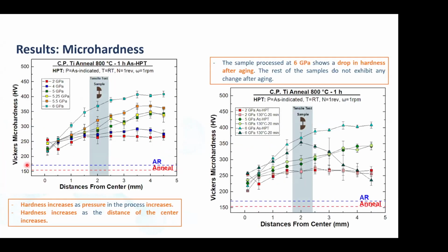So here is plotted the hardness of this kind of material against the distance from the center. And then you can see the effect of pressure on the hardness and the distance from the center. So 2 gigapascals, 4, 5, 5.25, 5.5, and 6, as you can see here. Then we get an increasing hardness, gradual at the beginning, but once we get to a higher pressure, there is a more significant step up in the hardness.